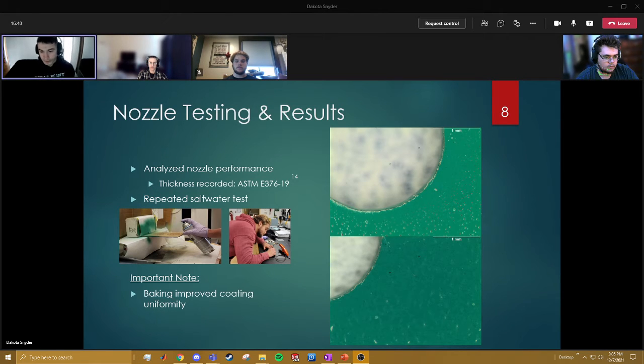3 types of tests were conducted in a controlled lab. An application test was done for 16 nozzles. This test checked for clogging and the ability to reproduce the same spray pattern. Coating thickness was also recorded for posterity and legitimacy, and the saltwater test was repeated for comparison of SD1 samples and verification purposes.